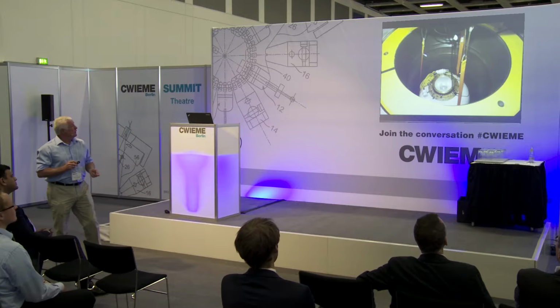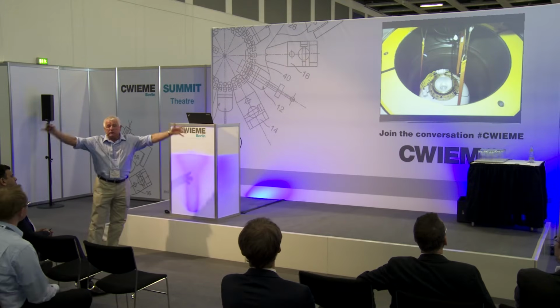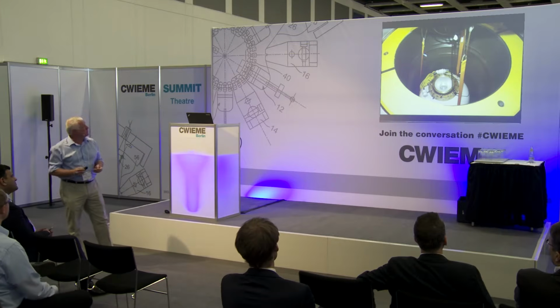Proof of concept of the FEA was that we strain gauged the real sphere for when it went to Pennsylvania State University for pressure test. There are only 2 chambers that I could find worldwide that could test a pressure vessel to 114 MPa. That was our design working pressure for the vessel. That was Pennsylvania State University. The other one was in Russia, and we had considered going to Russia for the testing. Here it's being lowered into the 60-inch inside diameter chamber. We're in the US now, so we're in inches.